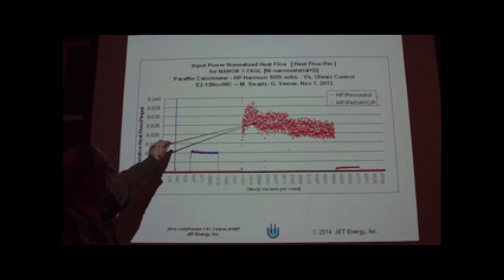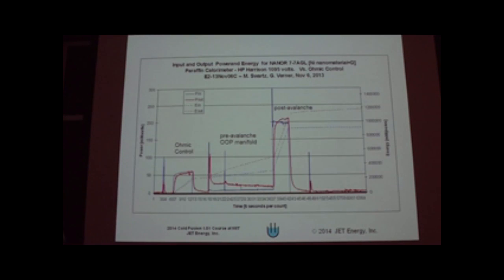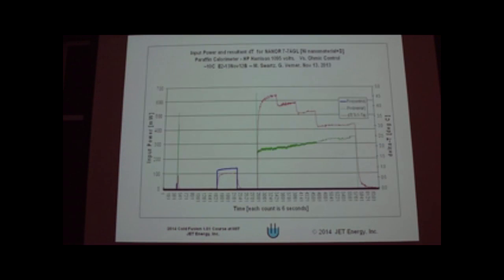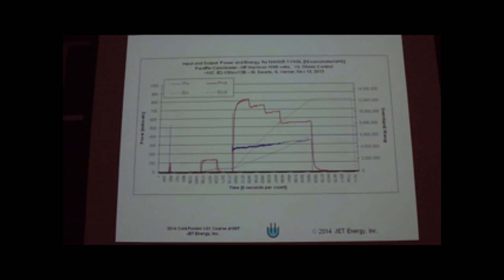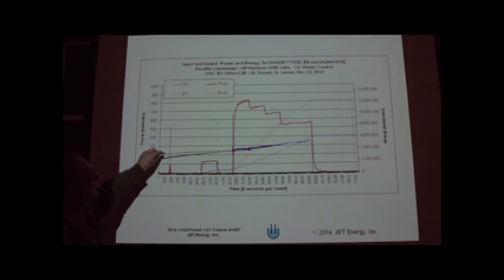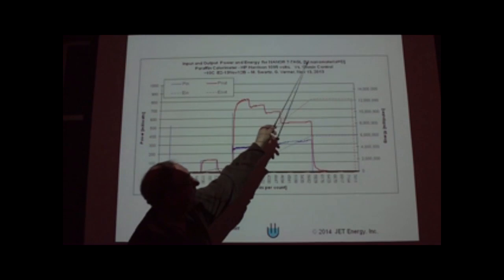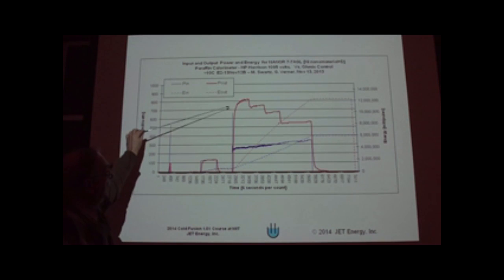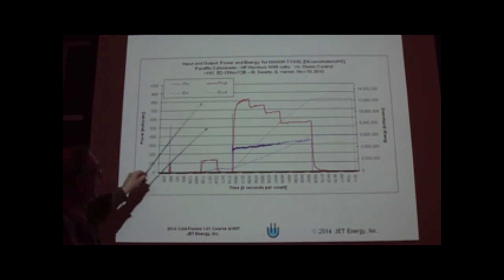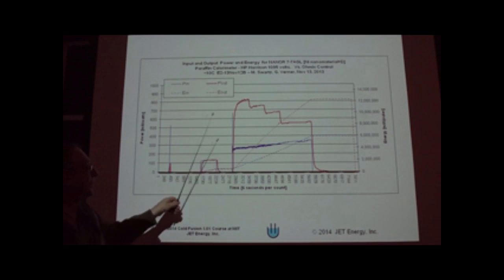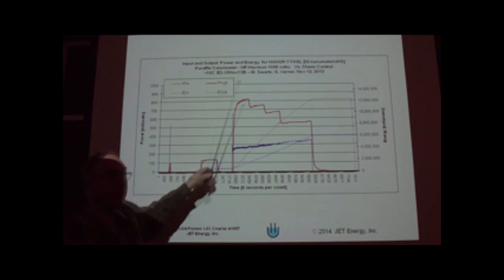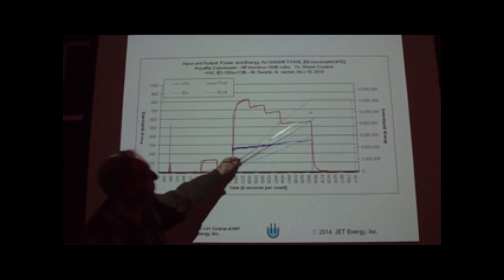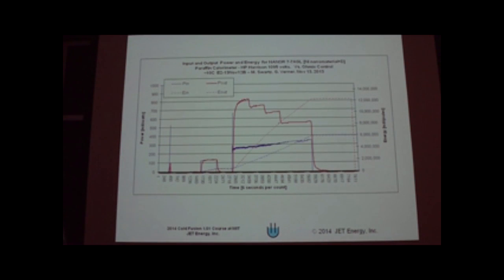And we also saw it for heat flow. Again, we take the ratio. This is before the avalanche. Here's after the avalanche, so we lose our excess energy. Here we can see that if we stay below the avalanche, see, here's our input-output. Here's the input to the NANOR, and the output, again, this is the nickel with the D, no palladium in this. Our energy gain is here to here. When we drive here, here to here, here to here, it's falling down. And therefore, these slopes are also falling. And eventually, if this came down to match, these two would be parallel, like they are here.